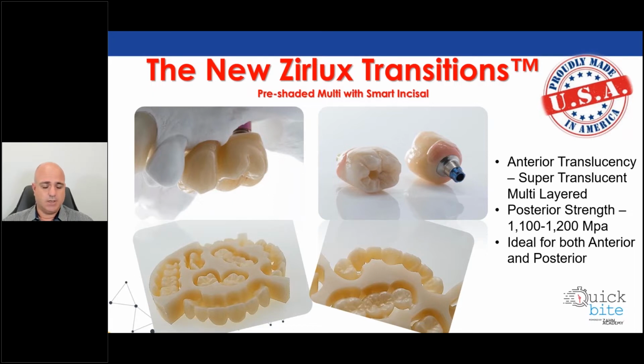It's really more of a transition, and hence the name, because that comes from the way these pucks are manufactured with a hybrid hydrocolloid kind of processing, whereby they create the raw materials in the zirconia into fine particles. It's a proprietary process, and it becomes almost, not liquid, but like liquid, so that they can actually layer it in such a way that there's no multi-layer as far as lines of demarcation. It's a true transition where from the cervical, you get a more increased chroma, and as it gravitates further up to the incisal edge, depending on the structure of the shade, there's more yttria introduced and therefore translucency.